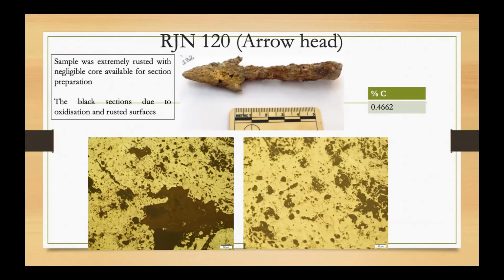If it actually hits and then tries to come back, when it hits, it will break, because 0.46% is a pretty low carbon, and it will not make the structure very hard. But I wanted to look at the microstructure, and that again created an issue, because it was extremely rusted with very negligible core area visible. The only thing I could understand was that the blackish sections were the oxidization and the rusted surfaces. So this actually made me understand that all that glitters is not gold. This object looked very nice to me, but actually I couldn't get anything out of it.